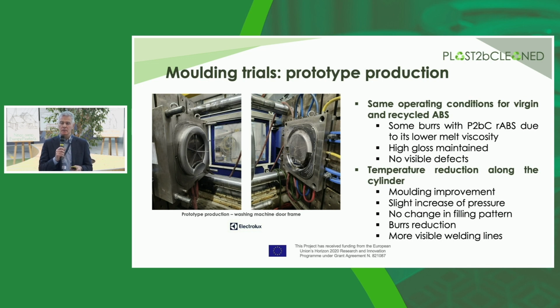At the same time, taking advantage of the high fluidity of the material, we tried to reduce a bit the temperature along the cylinder, and that was also possible because it was in reality an improvement in the process, because there was an increase of pressure, but the temperature was reduced by 15-20 degrees. Practically very small differences in the filling pattern, a small reduction of the bars, of course, it was good.